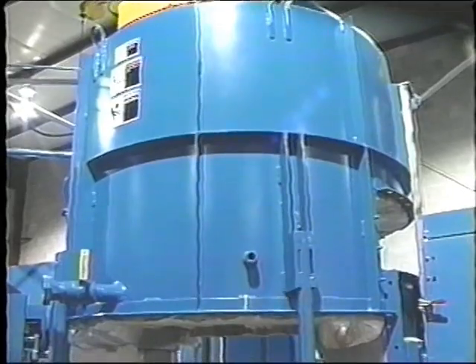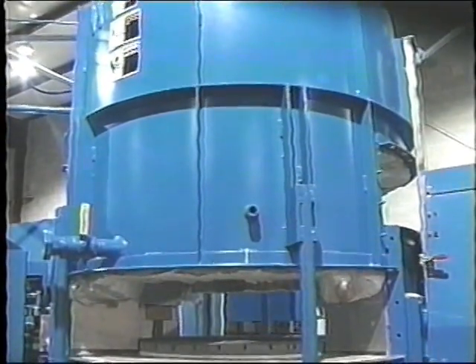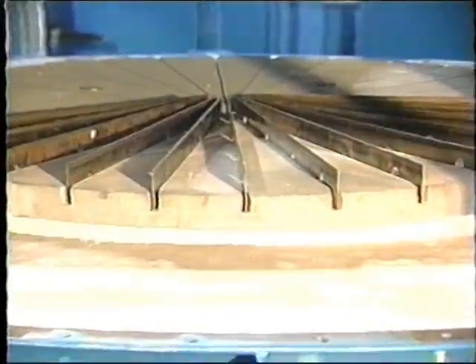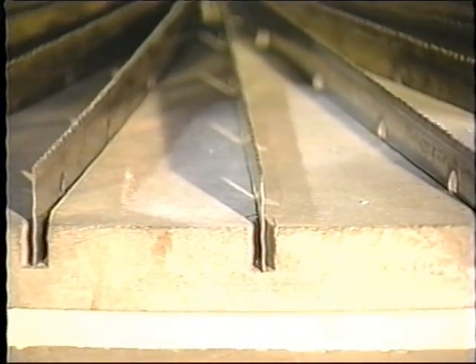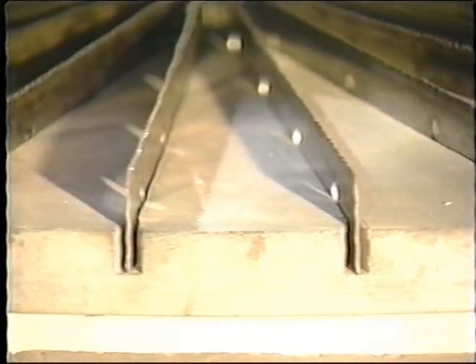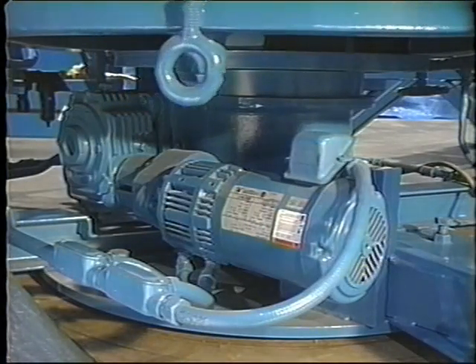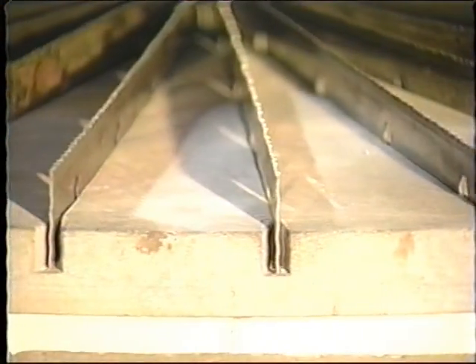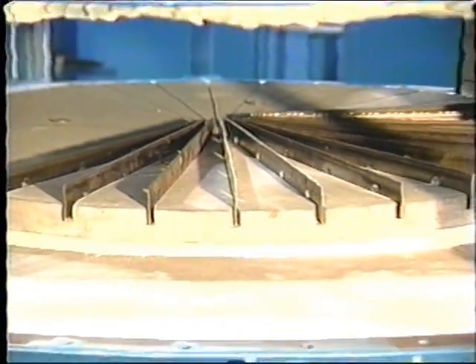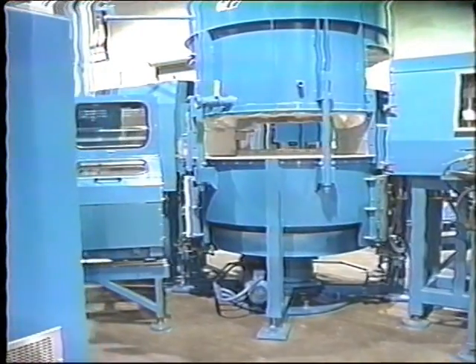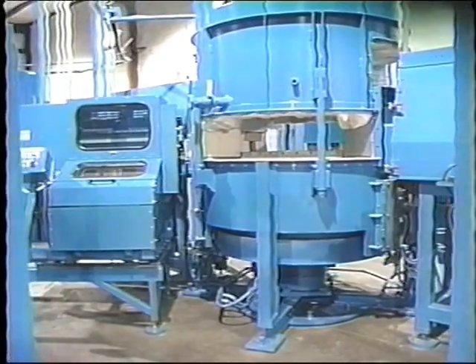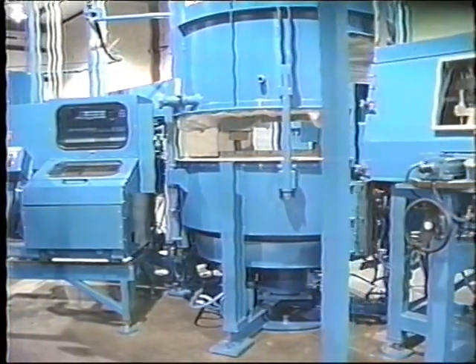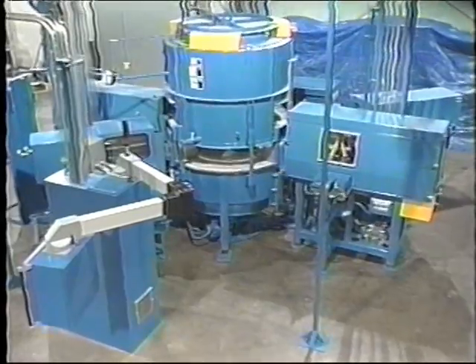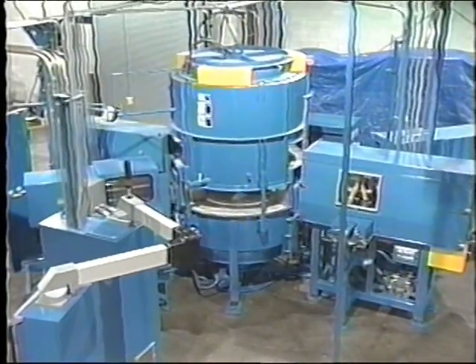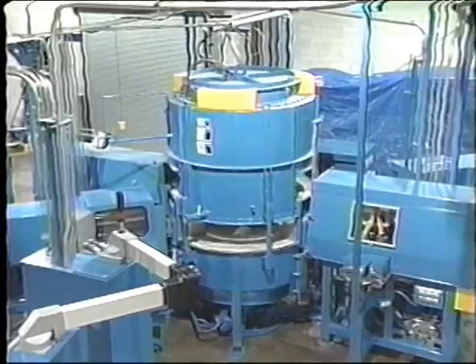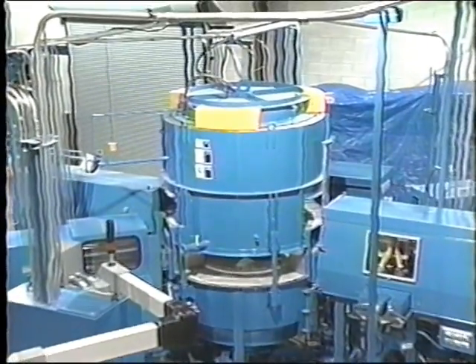The Seco Warwick rotary hearth furnace is uniquely designed for hot forming of hole saw blades. The furnace hearth is constructed of high temperature silicon carbide and has precision machine slots to accept the blades. The hearth is driven by a positive indexer drive. This combination provides a simple but accurate system for heating and transporting the blades. The furnace is electrically heated and is sealed to provide a positive pressure atmosphere for proper heat treating without scale. The outer portion of the furnace, including the roof, is designed to be removable to gain access to the interior and to the furnace hearth. The furnace roof can be also removed separately.